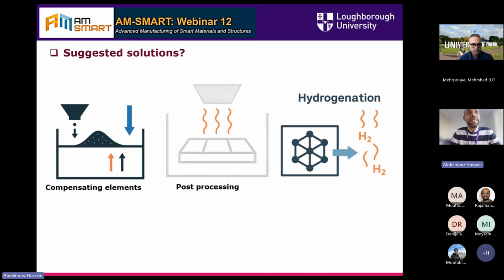The suggested solution for these things, in general, is that we will need to compensate the evaporated elements. This is the first one. The second one, to do post-processing. Post-processing is very critical for some materials. So for example, the lanthanum iron silicon one, we have to do almost 7 days of heat treatment to get rid of the secondary phases that we have, the iron-based and even the lanthanum-based one. So that was a very long process, but it's essential to get to the nominal compositions that you started.